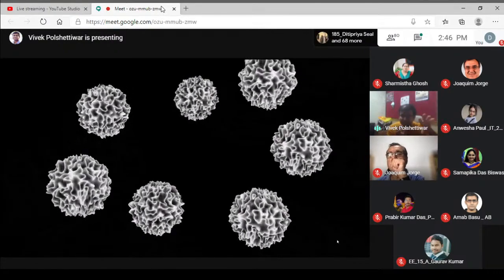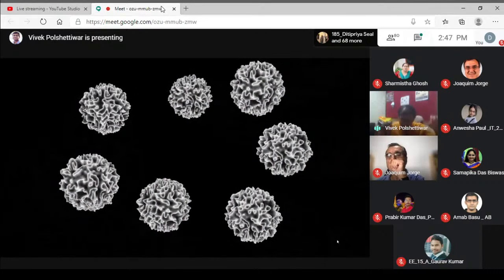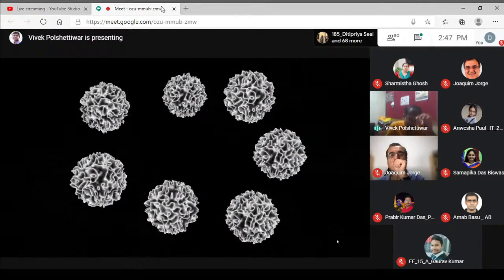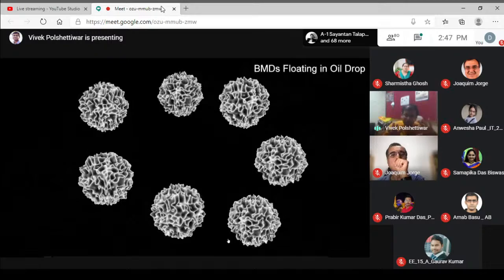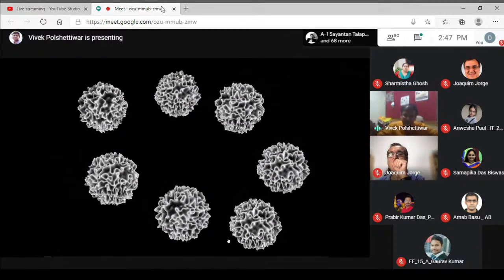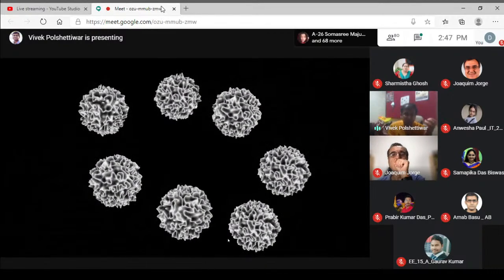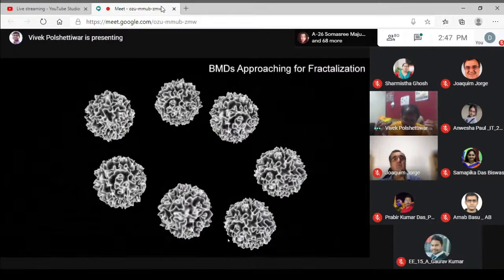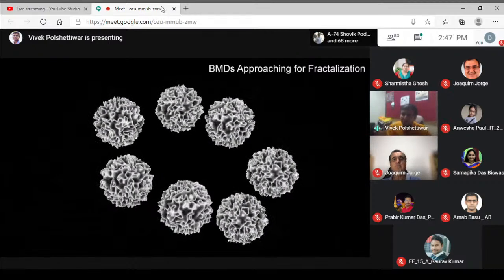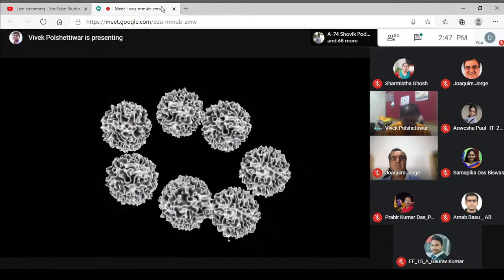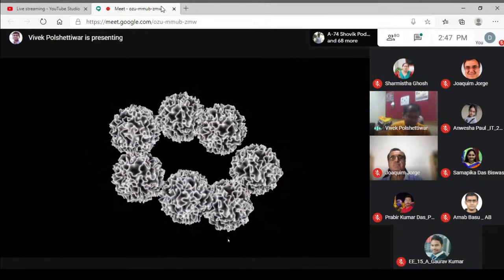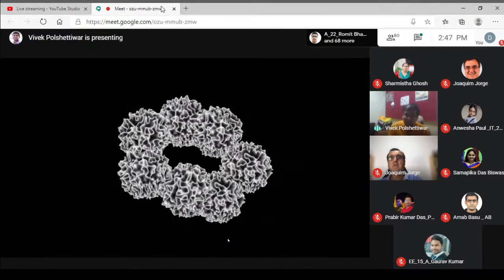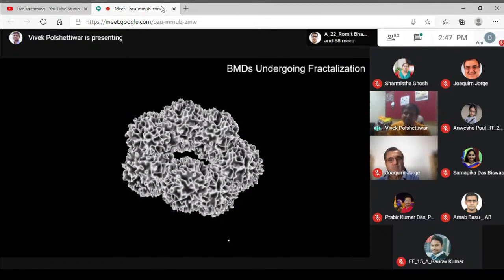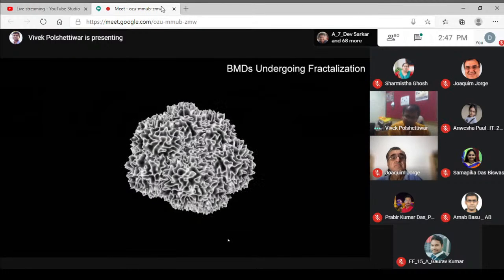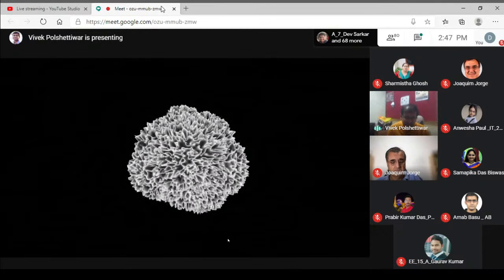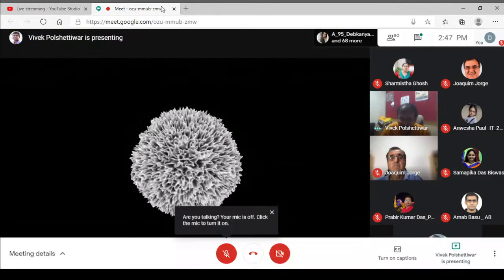So these are not nanoparticles, these are the reactors, these are the templates where I grew my nanosilica in those channels, right? Now if I keep these droplets away from each other, I get very small nanoparticles. However, if I force them together and some of them merge, you get a bigger droplet and I get a bigger nanoparticle. So this is how we tune the particle size. We can now get from 50 nanometers to 1200 nanometers by simply changing some reaction conditions, so that sometimes they stay away from each other, sometimes they merge, based on the requirement of the size of the particle.